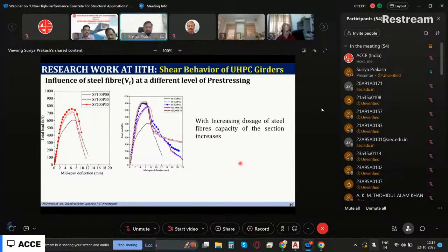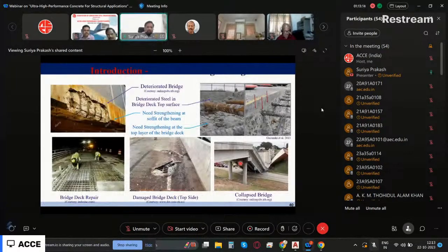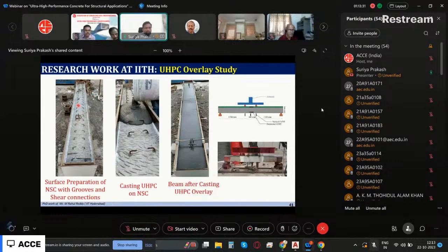Now all these things will go as a guideline for what we are developing for IRC and the design guidelines. Now this material can also be used for strengthening of the beam. So we evaluated, okay, for an existing beam, if I put this kind of an overlay, what we do is we chip the concrete at the top and we put a small layer of about, I think we used about 50 mm or so.